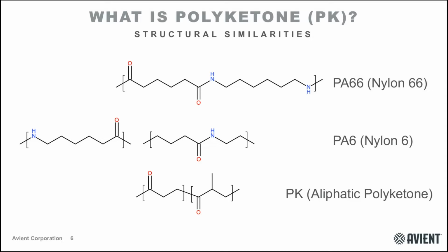These are all semicrystalline materials that contain carbon-oxygen carbonyl functional groups. And those are the structures shown in the red circles. Those are the oxygen atoms. However, polyketone noticeably lacks the backbone nitrogen present in the nylon amide bond. That's shown in the blue NH functional groups on the nylon 6 and nylon 6,6. And this makes polyketone much less hygroscopic than nylon 6 or 6,6. And as a result, the material properties are much less sensitive to moisture conditioning.